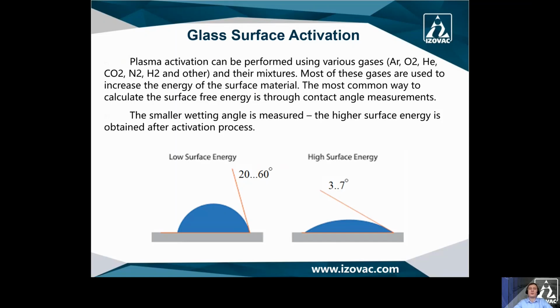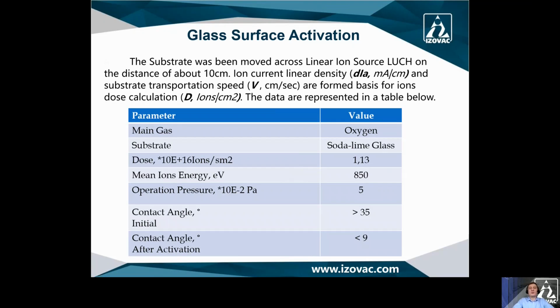The most common way to calculate the surface free energy is through contact angle or wetting angle. The smaller wetting angle is measured, the higher surface energy is obtained after activation process. Here is the wetting angle before activation and after activation. The conditions of experiments are as follows. The substrate was moved across linear ion source LUCH at a distance of about 10 centimeters. Ion current linear density and substrate transportation speed form the basis for ion dose calculation. The data are represented in a table below.